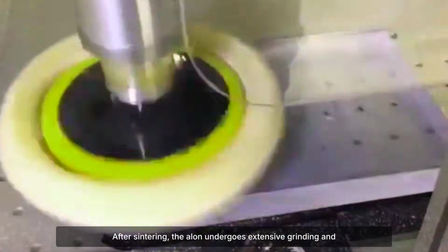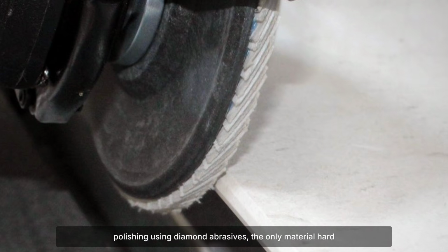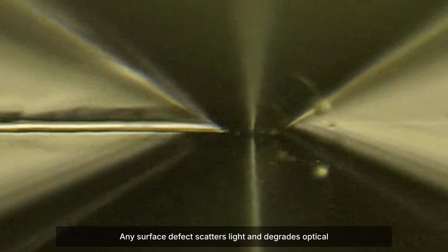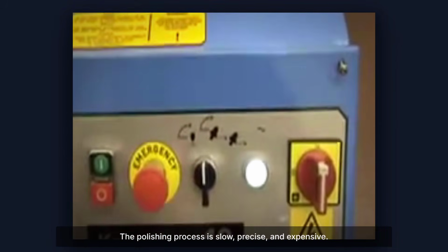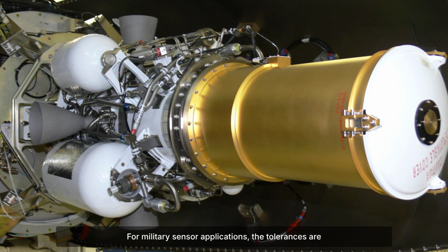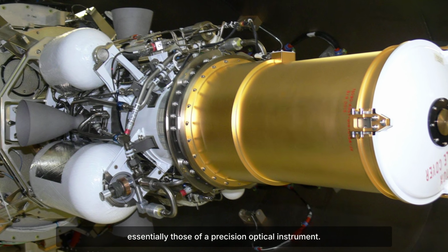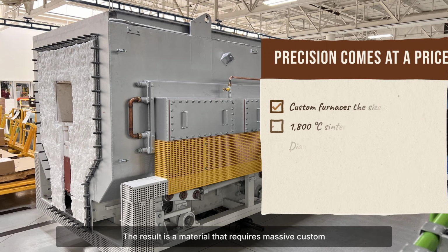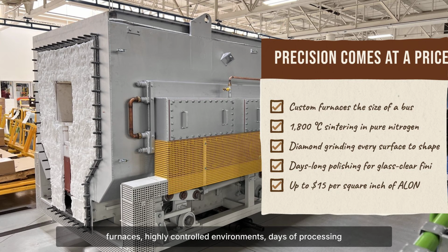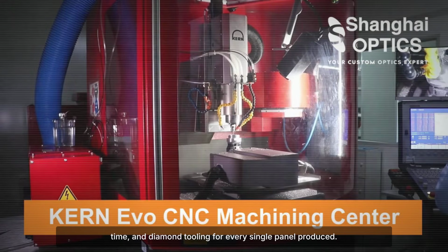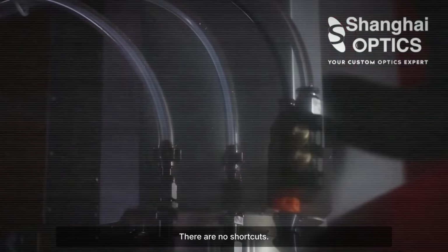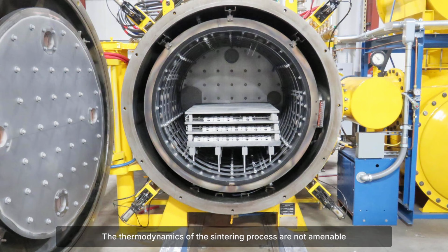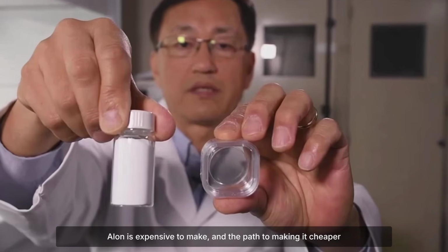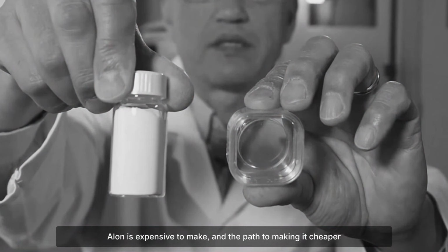Useless for most applications. After sintering, the Alon undergoes extensive grinding and polishing using diamond abrasives, the only material hard enough to work it. Any surface defect scatters light and degrades the optical performance. The polishing process is slow, precise, and expensive. For military sensor applications, the tolerances are essentially those of a precision optical instrument. The result is a material that requires massive custom furnaces, highly controlled environments, days of processing time, and diamond tooling for every single panel produced. There are no shortcuts. The thermodynamics of the sintering process are not amenable to easy improvement. Alon is expensive to make, and the path to making it cheaper is not obvious.